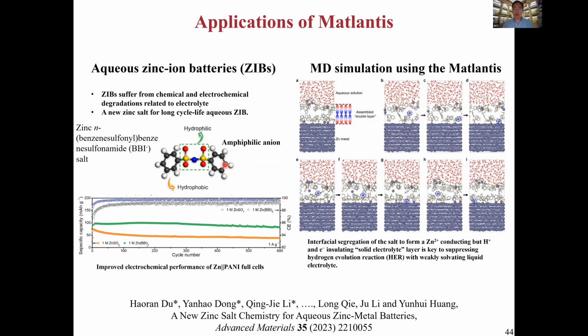And so when we looked at this electrochemical interface, what we found was that this zinc BBI salt has a very strong tendency to form almost like a solid electrolyte for zinc ion near the zinc metal. And also this is conducting to the zinc cation. So the zinc cation is able to transport across this, let's say, self-assembled SEI, if you will, although this is not permanent. If you remove the electrode, it's going to go back, redissolve into the water.